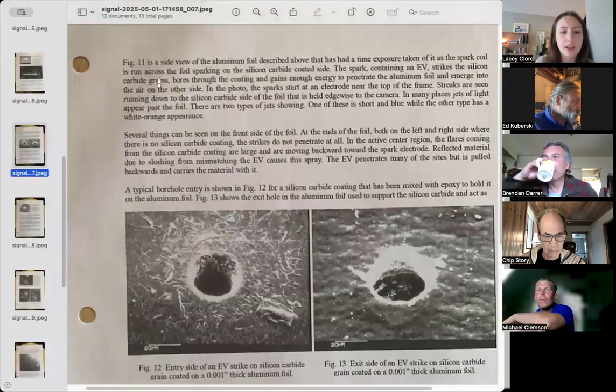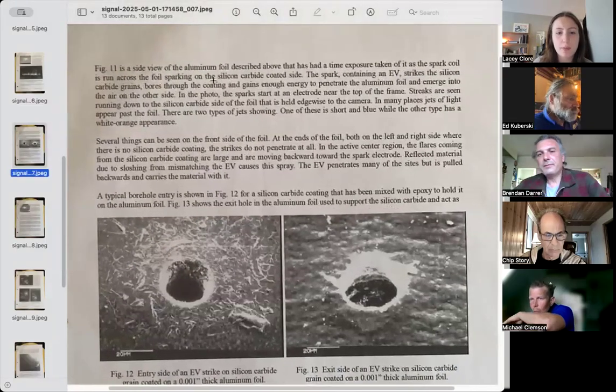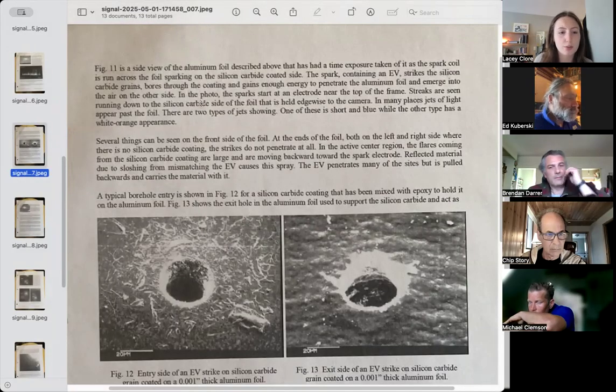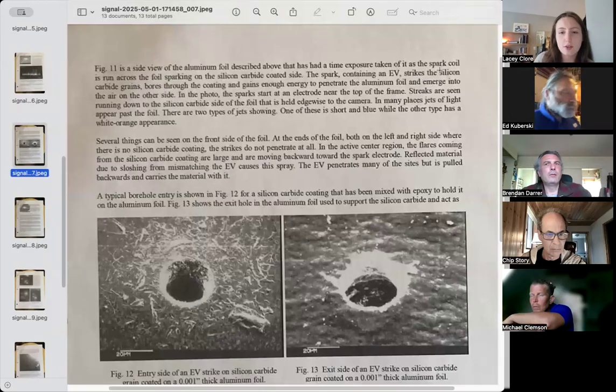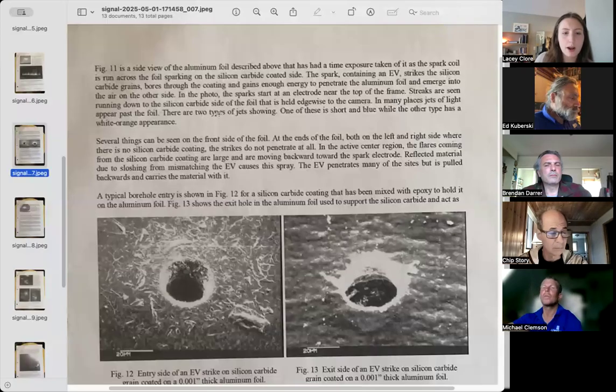Figure 11 is a side view of the aluminum foil described above that has a time exposure taken of it as the spark coil is run across the foil, sparking on the silicon carbide coated side. The spark containing the EV strikes the silicon carbide grains, bores through the coating, and gains enough energy to penetrate the aluminum foil and emerge into the air on the other side. In the photo, the sparks start at an electrode near the top of the frame. Streaks are seen running down to the silicon carbide side of the foil that is held edgewise to the camera.